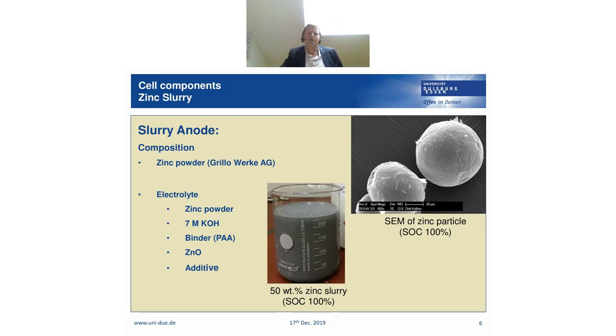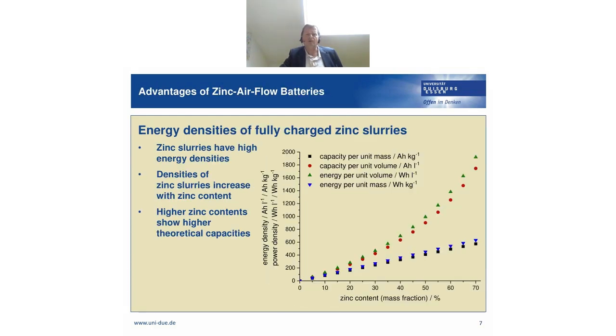Our electrolyte is made up of the zinc powder, and it's an alkaline electrolyte. We mainly use 7 molar potassium hydroxide, and the electrolyte is stabilized with the help of a binder. Mainly we use PAA, polyacrylic acid, and we add some zinc oxide for the purpose of suppressing hydrogen evolution. And sometimes we add one or two additives to improve the performance.